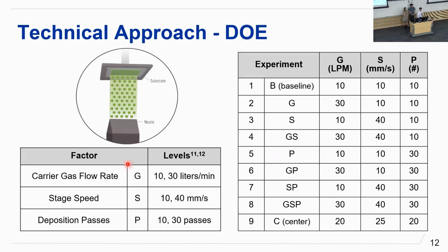We have a three-factor, two-level experiment where the first factor is carrier gas flow, represented by G in the table on the right. We had a low level of 10 liters per minute and a high level of 30 liters per minute. The second factor was stage speed, represented by S on the table on the right. We had a low level of 10 millimeters per second and a high level of 40 millimeters per second. And thirdly, we had the factor of deposition passes, represented by P on the table on the right, which had a low level of 10 passes and a high level of 30 passes.